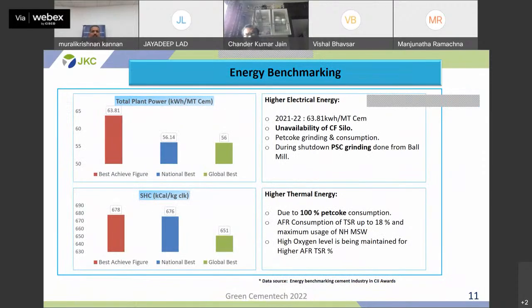Things which you cannot measure, you cannot control. So this is just a comparison of our best achieved figure along with national best and global best. In terms of total plant power, our best achieved figure is 63.81, and we already have a roadmap to achieve 58 units per ton of cement. Our specific heat consumption is very close to national best, even with 100% pet coke and 18% TSR.